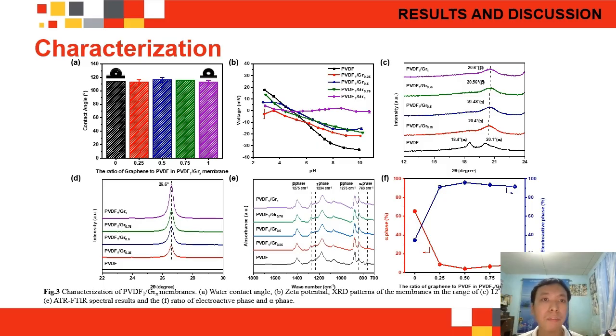In FTIR analysis, the addition of graphene reduces infrared absorbance due to its strong carbon absorption, and the alpha phase peak at 763 disappears. Meanwhile, the beta plus gamma electroactive phase at 840 increases significantly from 34.58% to 95.85%, while the alpha phase decreases to 4.14%.